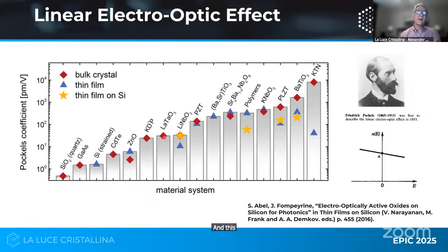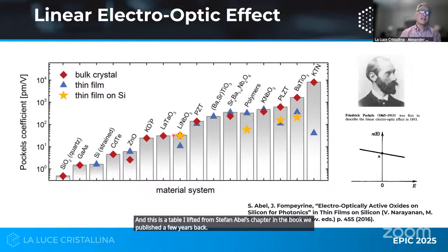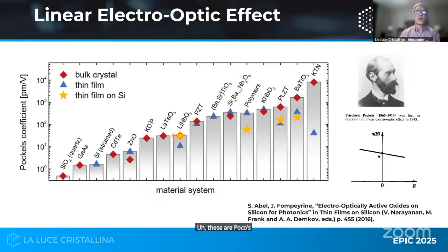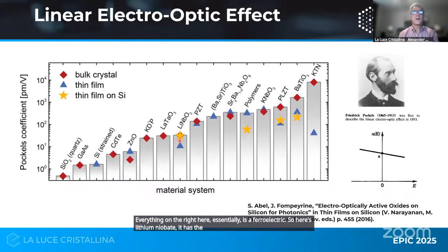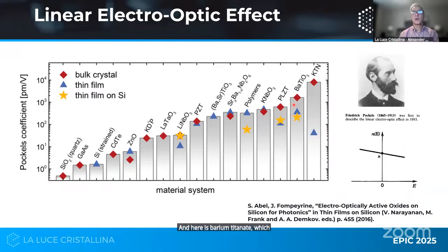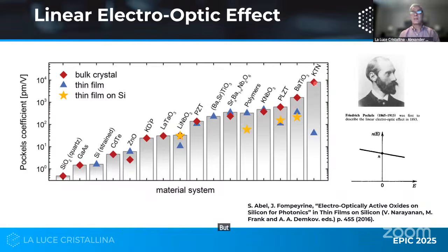And this is a table I lifted from Stefan Abel's chapter in the book we published a few years back. These are Pockels coefficients for a lot of good materials, and you can see that everything on the right here essentially is a ferroelectric. So here's lithium niobate. It has the Pockels coefficient of 35. And here is barium titanate, which in the bulk form has a Pockels coefficient of 1,300. Potassium tantalate is better, but it's potassium and tantalum, and so they're not very good for silicon manufacturing.